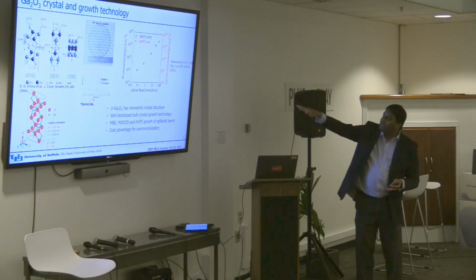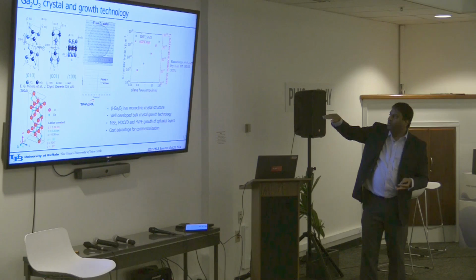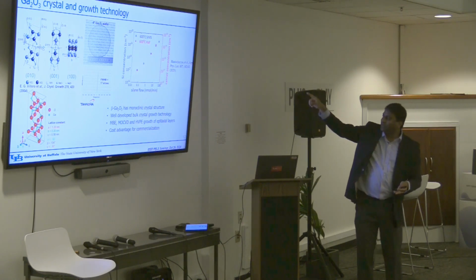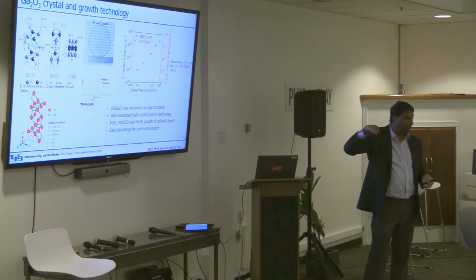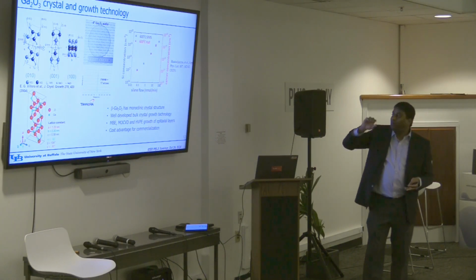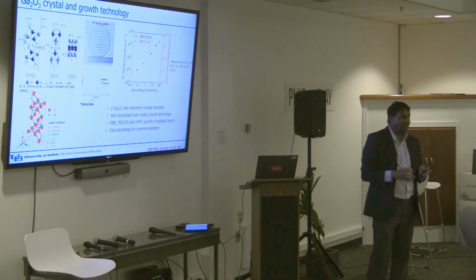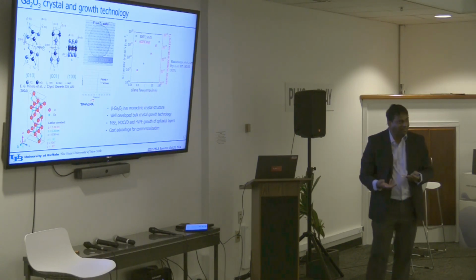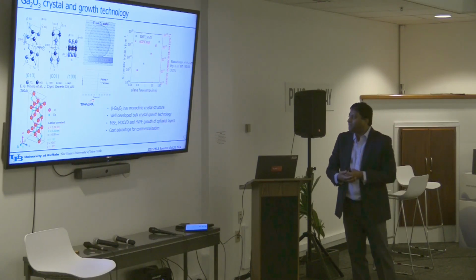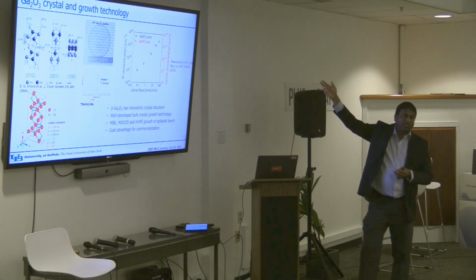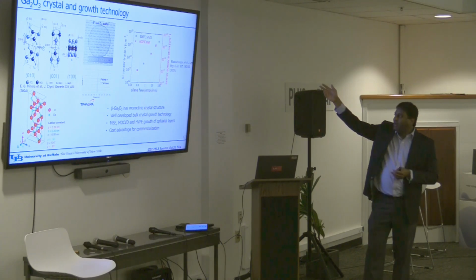Now on the right you see that you can have very high dopant control. This is showing 10^17, but there are recent results where you can go to 5e15 doping, right? Very low doping. You want very low doping for your drift layers, 20, 30 kilovolts. You need to have very low doping, otherwise you break down early, right? And you want high doping because you want to make good contacts, right?